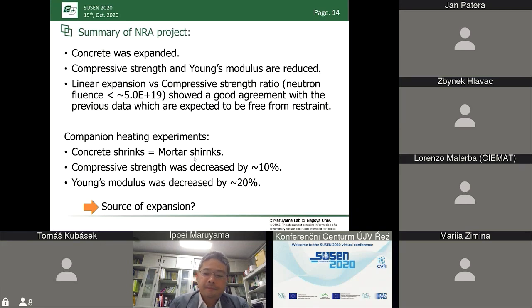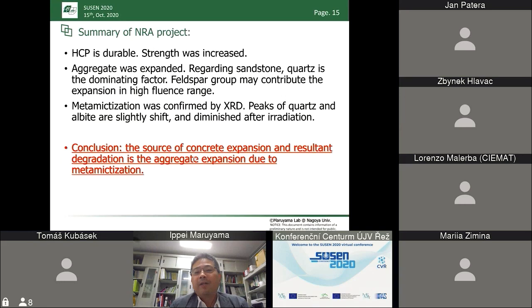And we found that the aggregate can be expanded, especially the andesite is very sensitive, while the hardened cement paste is very durable against the neutron irradiation. So we found that the source of the concrete degradation is the rock-forming minerals, which are affected by the neutrons, which makes the amorphization and shows the reduction of the density.